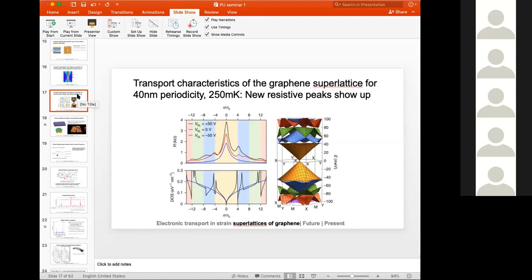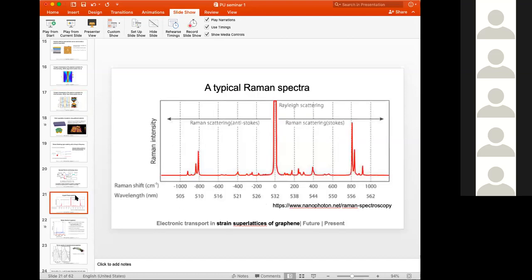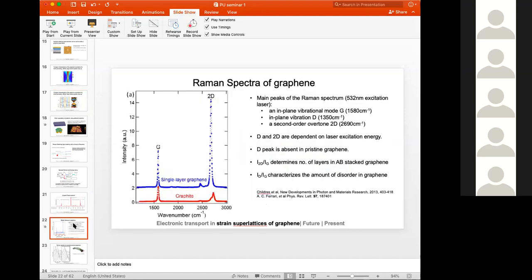Just maybe first one comment to Shadnik's question: the Raman shift going down basically means your phonons are softening, their energies are coming down, stiffness is coming down, and with strain you are basically having softer phonons. That's basically what is happening.